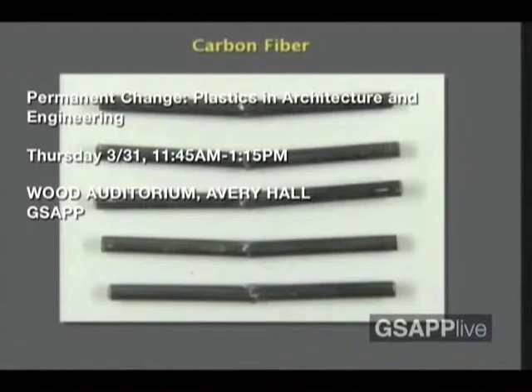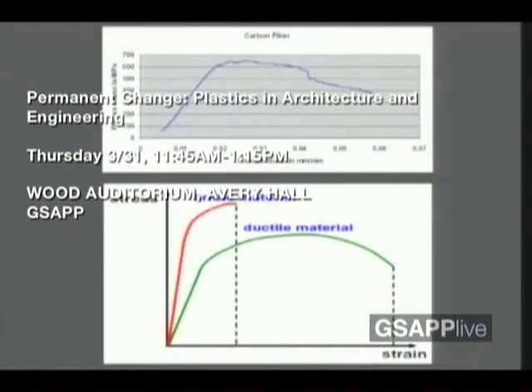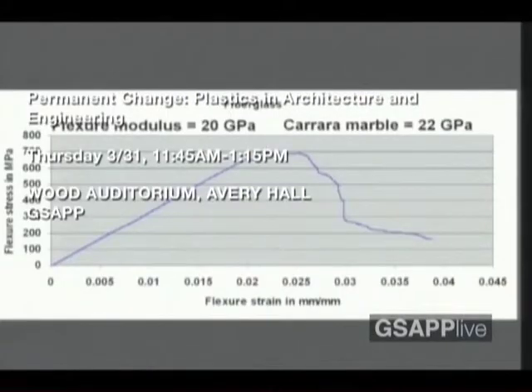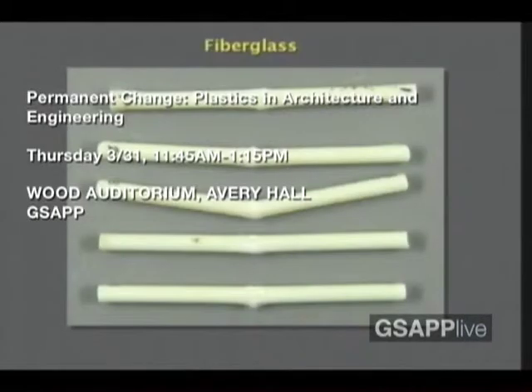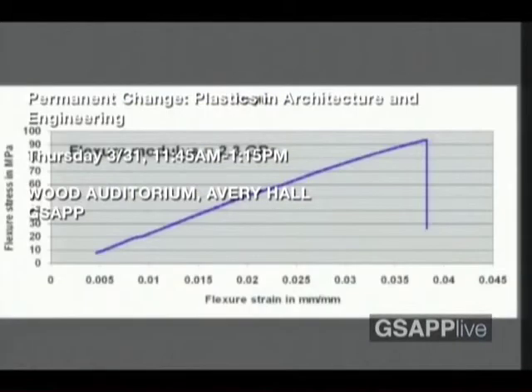Here's the kink behavior, the kink failure that occurs in fibrous materials. The plastic matrix fails, and then fiber by fiber gets broken. And again, just to emphasize that point, this is sort of looking like ductile behavior in this fiber-reinforced material. And maybe Jan will have more to say about that in a few minutes. And now we look at fiberglass. Here's the flexure modulus at 20 gigapascals. We're right in the range now of what we might want for Carrara marble, and we have a similarly pseudo-ductile behavior and the kink behavior you see in fiberglass.